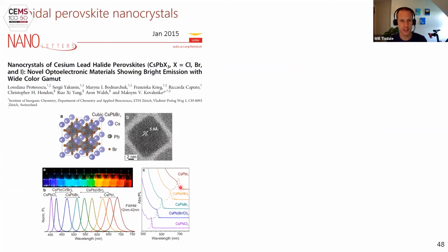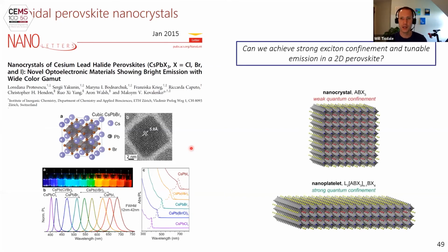If you look closely at the absorption spectra of these different cesium lead halide nanocrystal formulations, you'll see that they do not look like the absorption spectra of quantum dots. They look like the absorption spectra of bulk semiconductors, that they're very weakly confined. These cesium lead halide nanocrystals are loosely quantum dots. There's some quantum confinement, but not nearly as much as you find in a cadmium selenide quantum dot or a lead sulfide quantum dot. And we were interested in pushing that further.